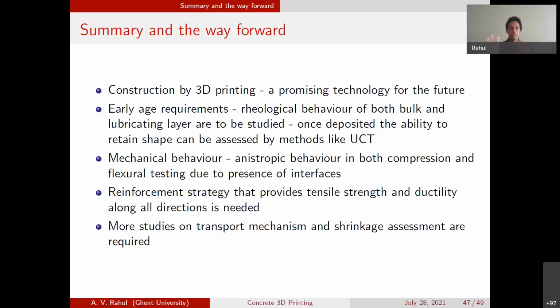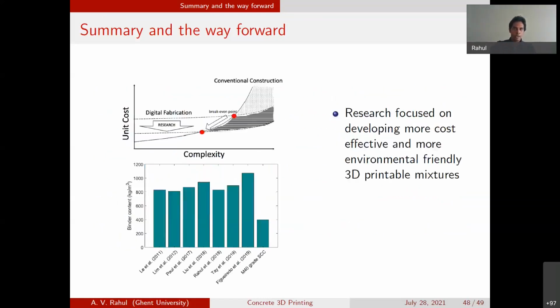So the post-structure assessment in some of the published literature indicates that the transport properties, particularly at the interlayer, are likely to be higher in printed concrete. Shrinkage assessment and mitigating strategies is something that we may need to look at when we look at the long-term performance of printed concrete.